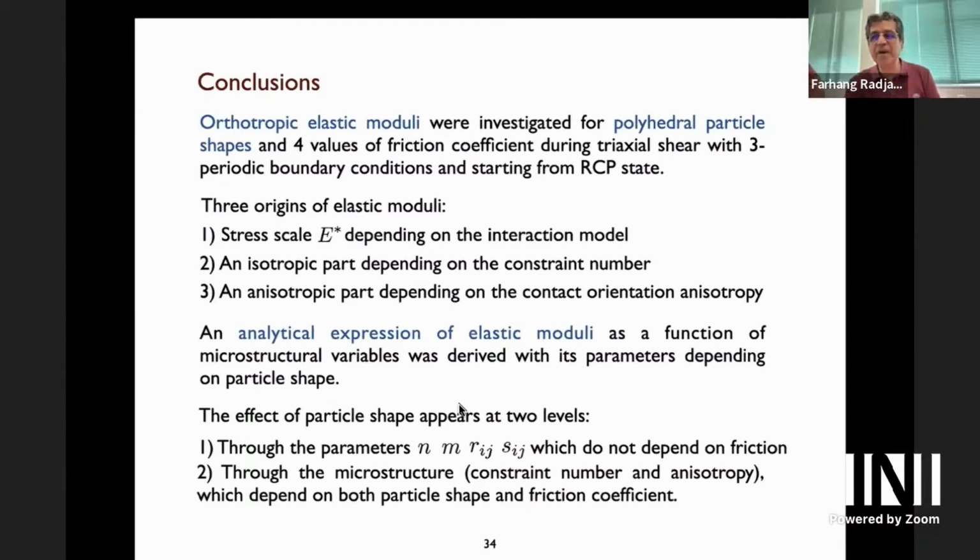You know, when face-face contact transforms, for example by rotation into an edge-edge contact, if we change the values of the stiffnesses, it can induce local instabilities in the simulation. So we kept them as they are, and I agree with you. This is an approximation. Of course, you see that when we have face-face contacts, we may have 10 contact points or even more. So we are taking all of them into account.